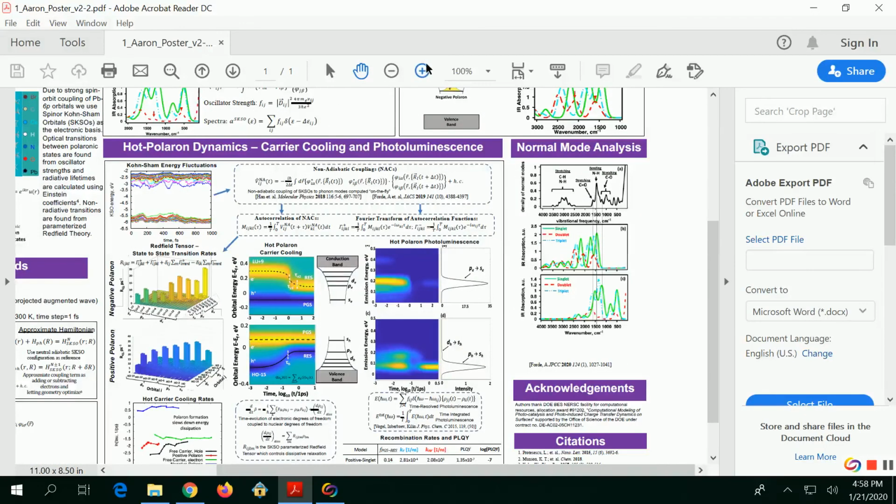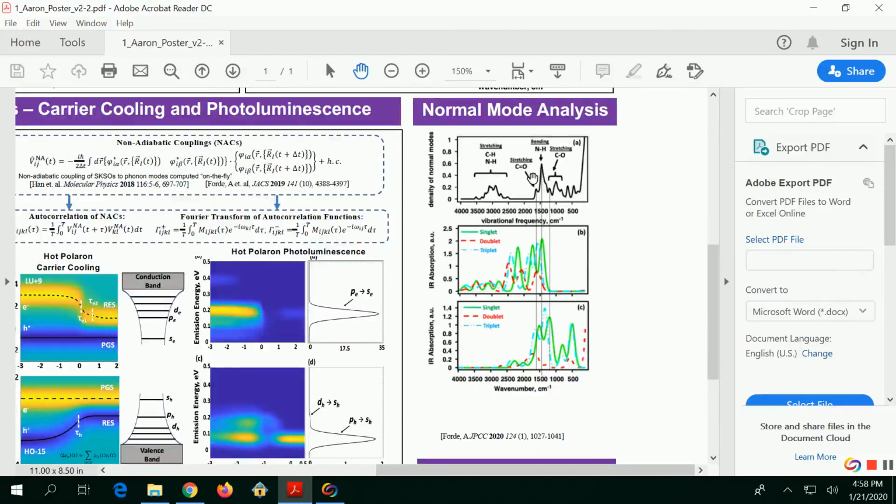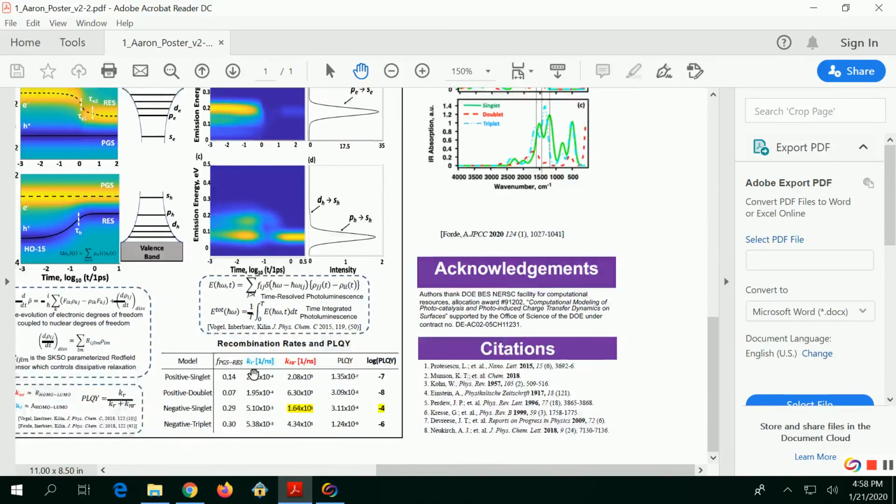So yeah, my interpretation would be anywhere where you have carboxylate contributions in the normal mode, those would be significant, whereas the ammoniums, even though there's a big peak there, don't contribute that much. So the singlet doesn't have any active vibrational modes in resonance with it, while the triplet does. So that's how they explain the 2 orders of magnitude difference in the non-radiative recombination.